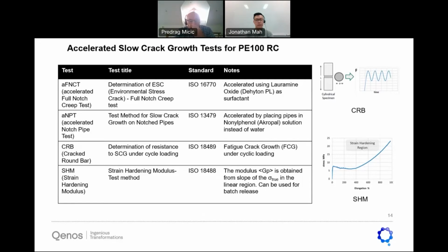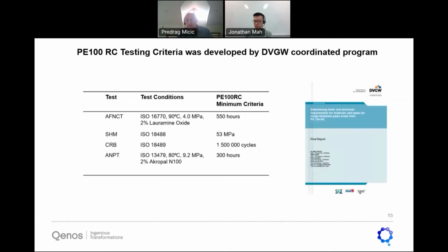And there is the strain hardening modulus test, which is the bottom right picture, which is sort of a tensile test, but done at 80 degrees. And this is the test that is proposed to be a QC or QA test. So these are the 4 tests that will accompany the PE100 RC classification in the standards. The PE100 RC testing criteria was developed by the DVGW coordinated program.